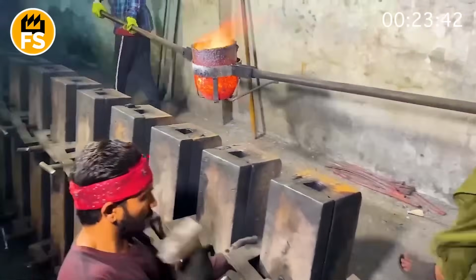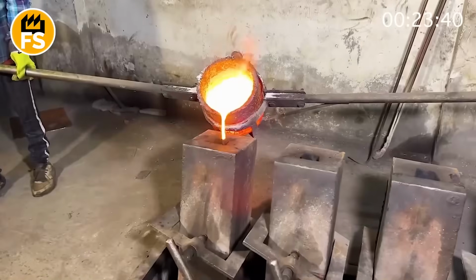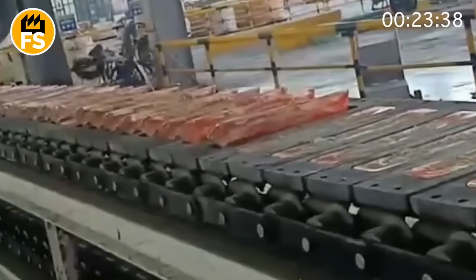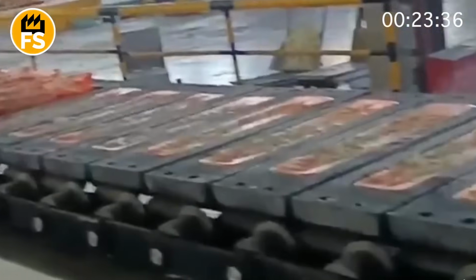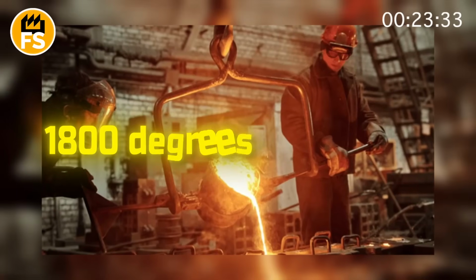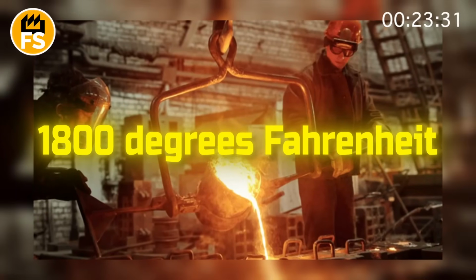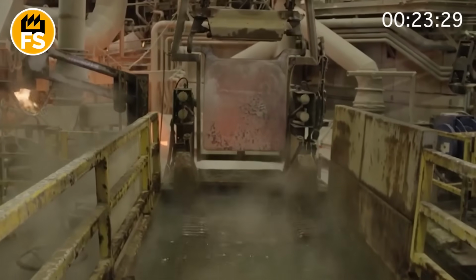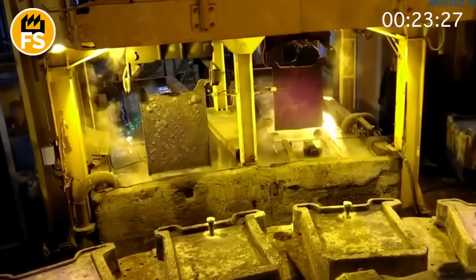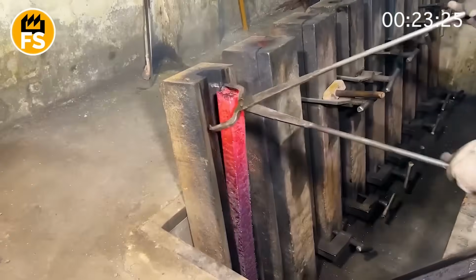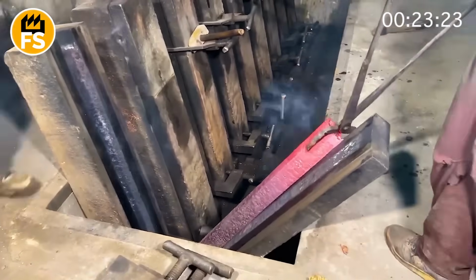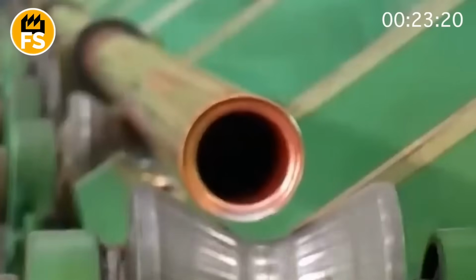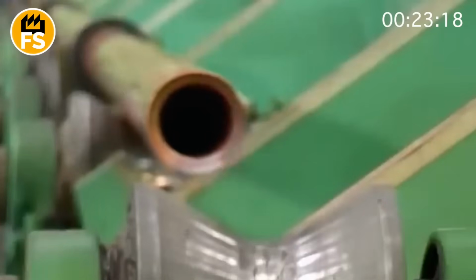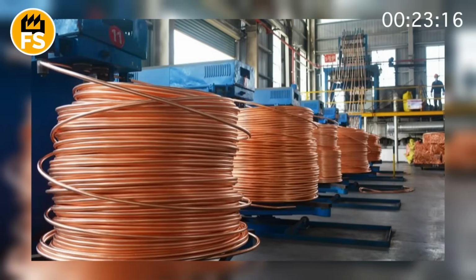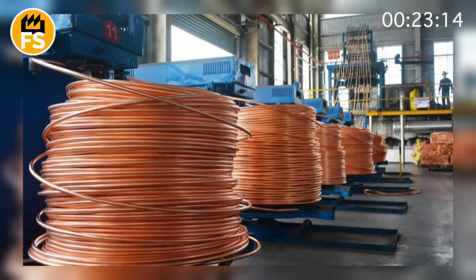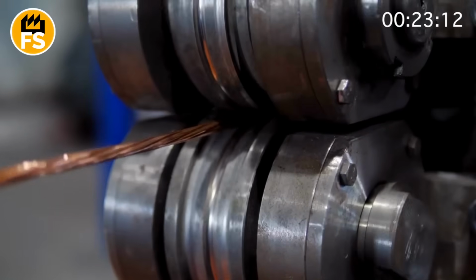The purified copper is ready for forming. The molten metal is poured into special molds, ingot molds. The molds are preheated to a temperature of about 1,800 degrees Fahrenheit to avoid thermal shock. Slow, controlled cooling allows the copper to crystallize with the correct structure. Perfectly uniform ingots weighing from 50 to 100 pounds or cylindrical billets 6 or 8 inches in diameter are formed. These billets are the basis for future cables. They go to the wire drawing shop where the next transformation takes place.